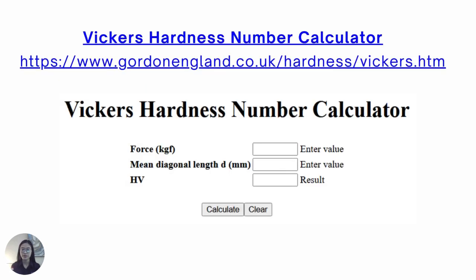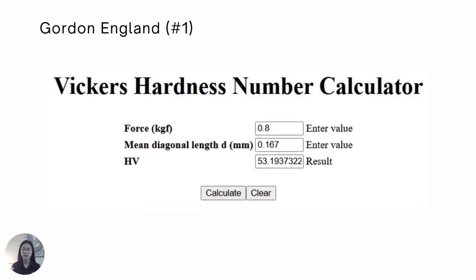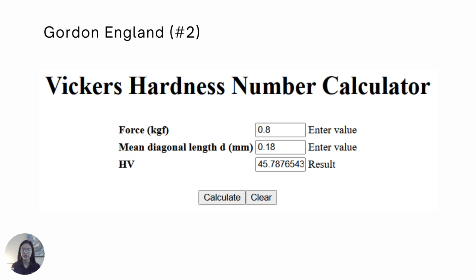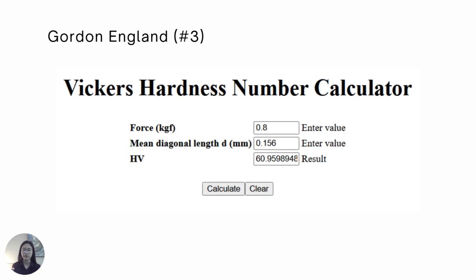So for the first one, I used a Vickers hardness number calculator from Gordon England. This is the result for the first indentation, with the force being 0.8 kgf, and the mean diagonal is 0.167, making the HV 53.19. And this is for the second one. The force is the same for all of it. It just differentiates in the diagonal length. So for this one, it's 0.18, making the HV 45.7. And then the third one, with the mean diagonal of 0.156, the HV is 60.9.